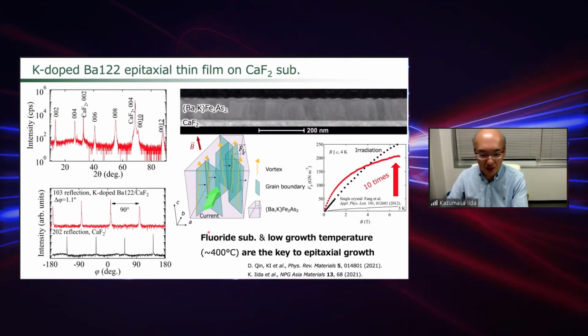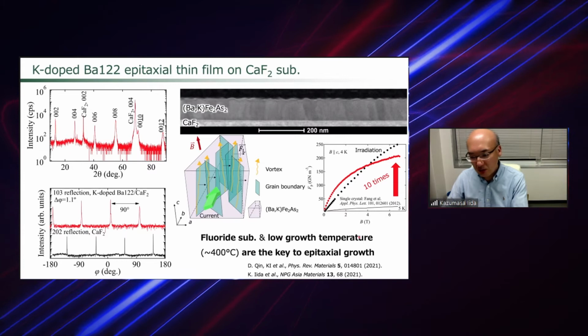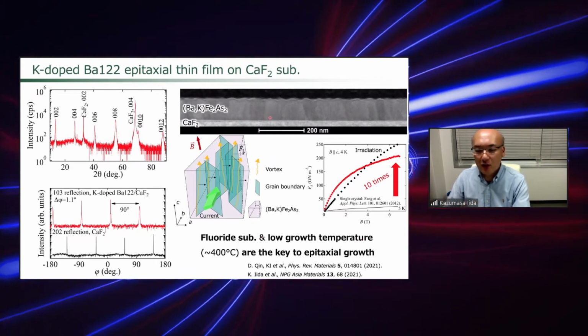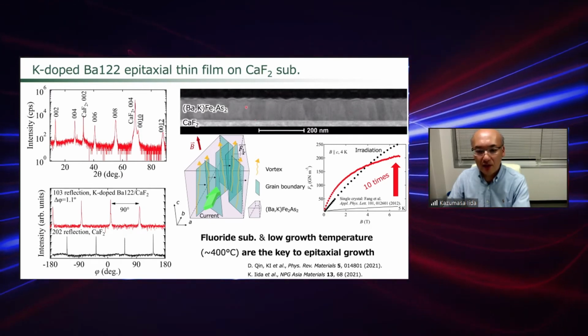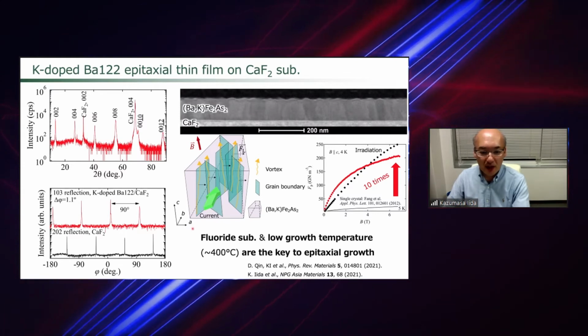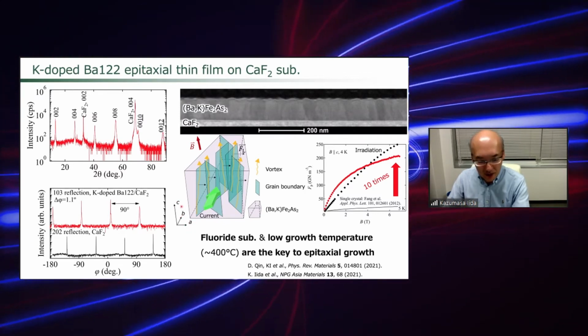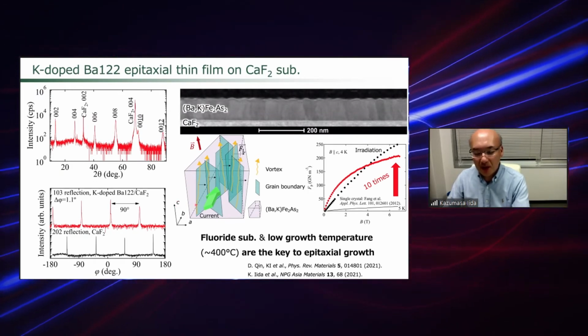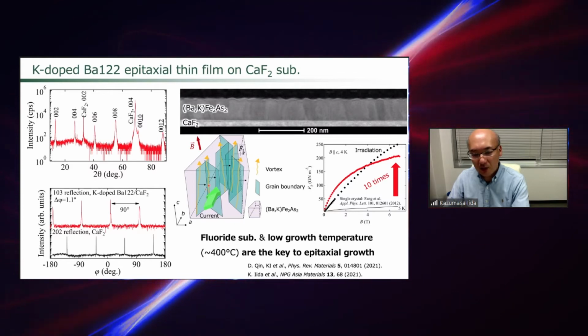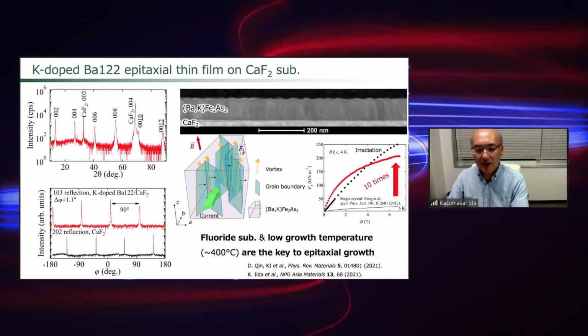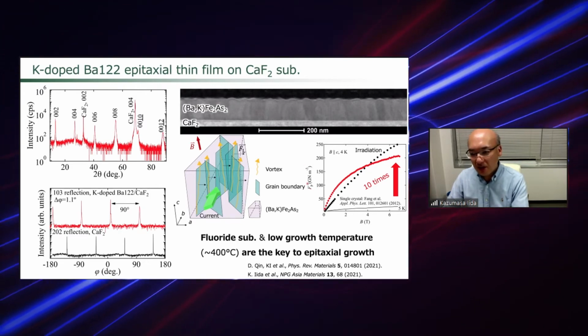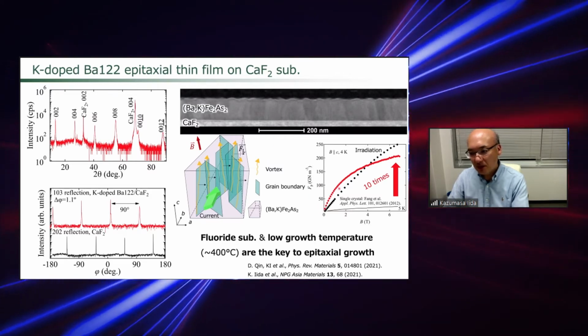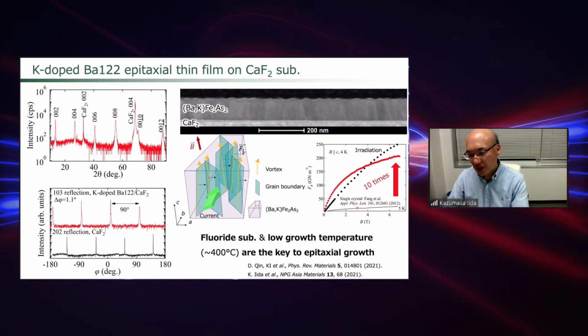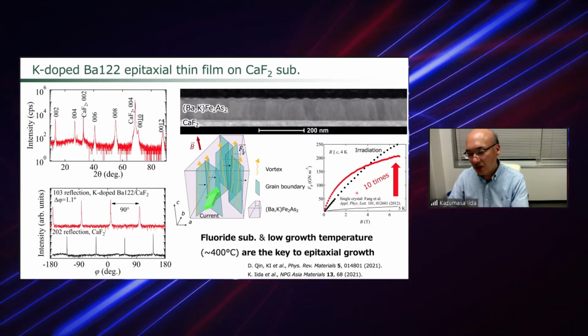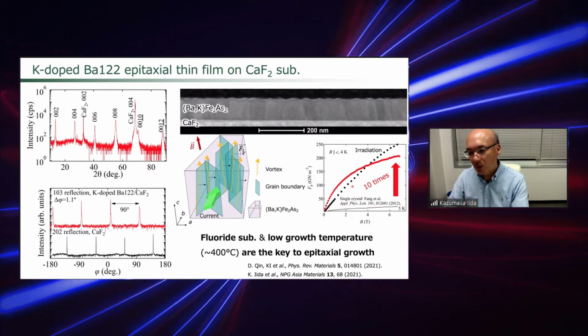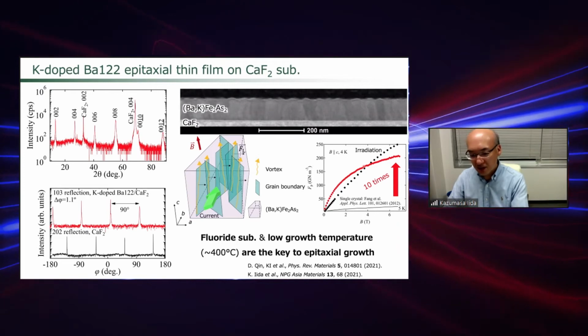The key to success is to employ the fluoride substrate as well as low growth temperatures. Here you can see that columnar grains grew almost perpendicular to the substrate, and each grain rotates around the a-axis or b-axis as well as the c-axis. So a lot of grain boundaries and networks are created inside the material, and these defects work as very strong pinning centers. And here is the pinning force density of our potassium-doped barium 122 thin films. As you can see, the pinning force density is almost 10 times higher than the pristine single crystals and comparable to the heavy-ion irradiated samples.